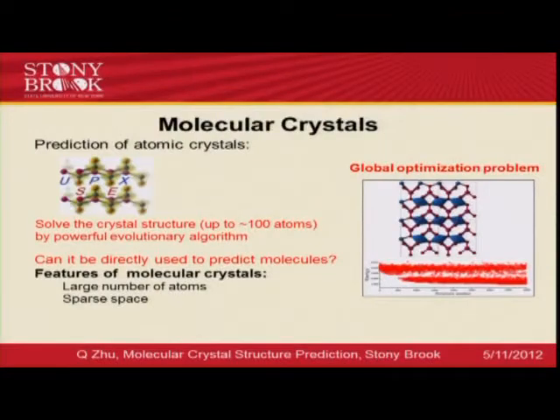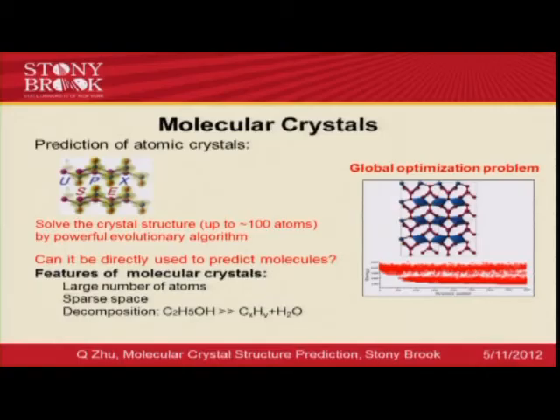One might speculate whether it is possible to directly use this method to predict molecular crystals. However, we have to understand that molecular crystals are quite different from normal atomic crystals, because they usually have a large number of atoms and contain much sparse space. This indicates that the configurational search space could be very huge.